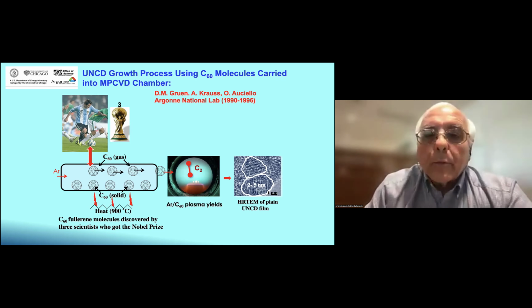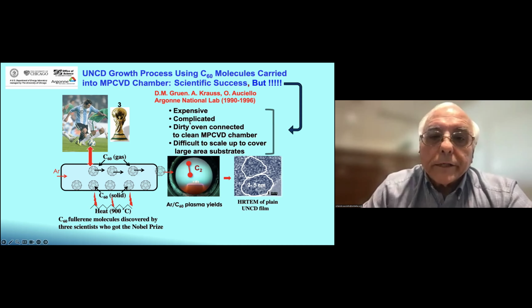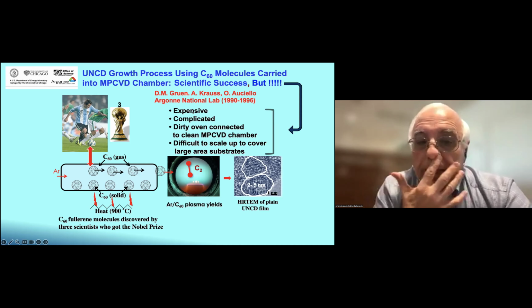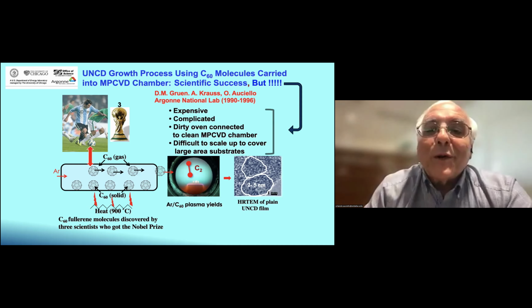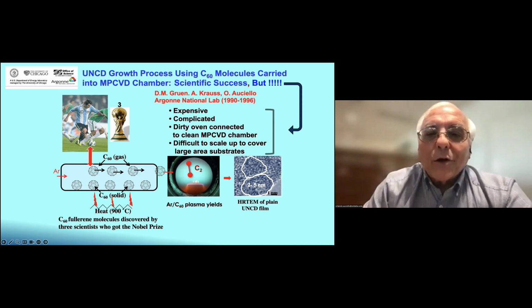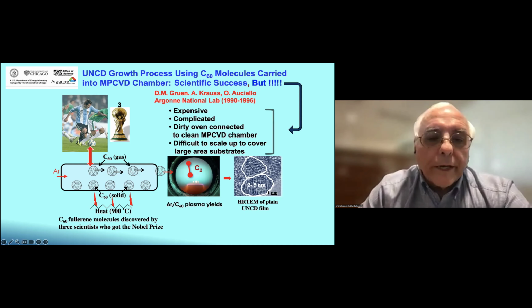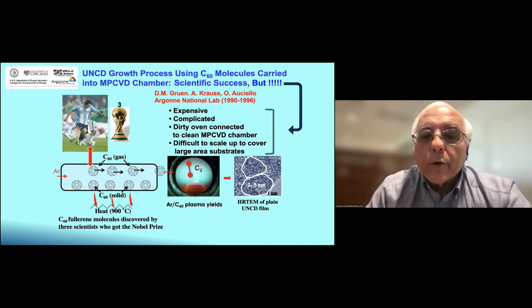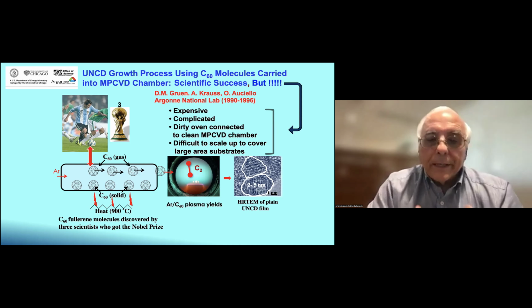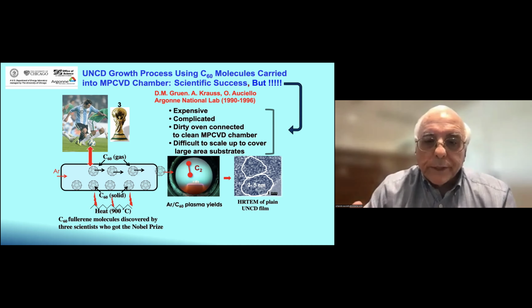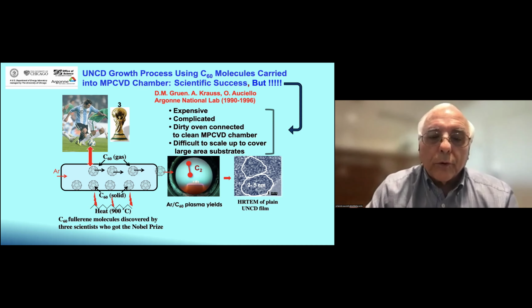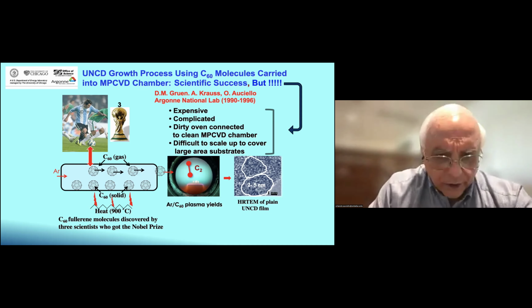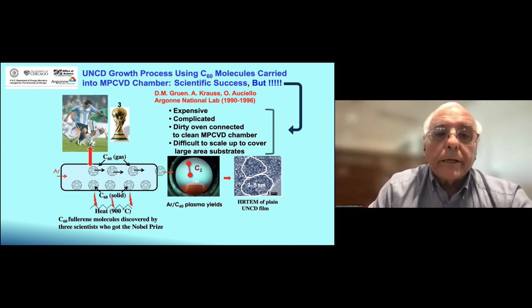However, I was very interested in bringing this to the market, and it is very expensive if we have to buy 10 grams of C60 fullerene molecule for $5,000. Complicated, a dirty oven creating a lot of soot connected to a high clean vacuum system, not good. And we didn't see how we were going to be able to scale up the process to grow the UNCD on large areas to do the low-cost UNCD growth needed for bringing it into the market.